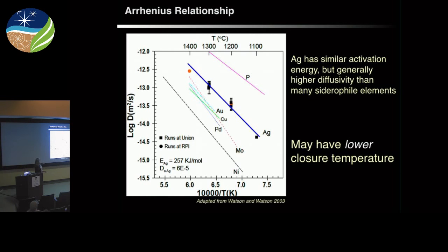And here is the Arrhenius plot of this data. So here again is the inverse of temperature versus the log of the diffusivity. And here's our new silver data up here compared to my PhD thesis data of a bunch of other things, not silver. We see the slope is very similar, but it's offset. Silver diffusion is actually quite a bit faster than a lot of our other siderophile elements, including palladium. And here's nickel diffusion down here, just for reference. Okay, so because it diffuses faster, it might have a lower closure temperature than we had looked at before.